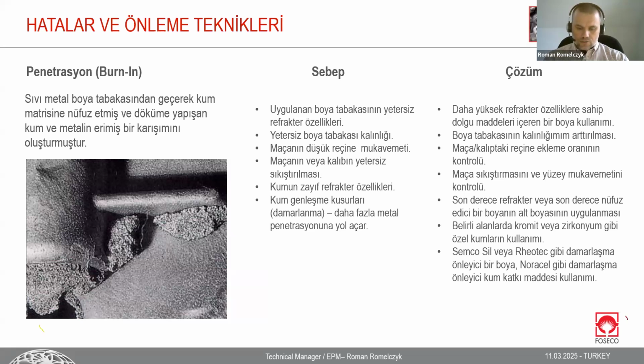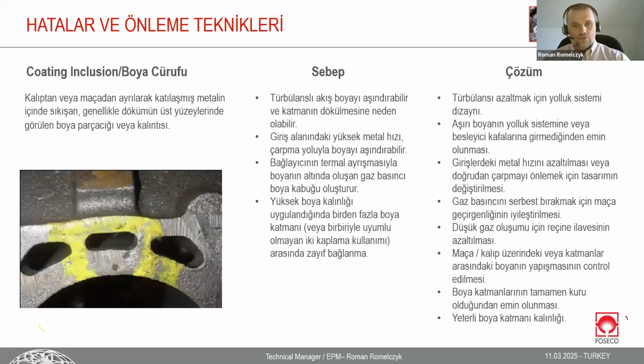Okay, another one, coating inclusions, of course, a lot of possible root causes as a high speed of molten metal. So we can say turbulent flow, velocity as well. Also the venting. The venting of the mold or core. And of course, the running gates and mold itself, if it's destroyed somehow, it's crushed in the running gate itself, it's not properly covered by coatings. So the molten metal during a high speed can take some particulars from the mold wash and agglomerate, locate this washed part of core or mold somewhere in the castings, what is visible on the picture.